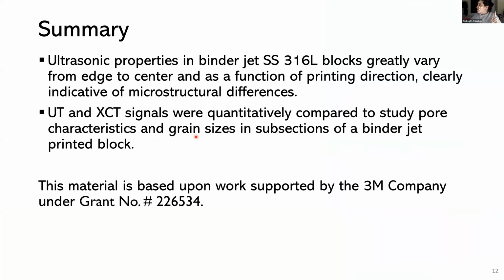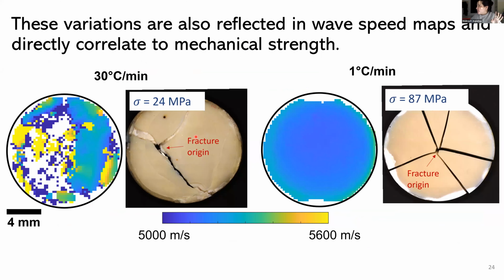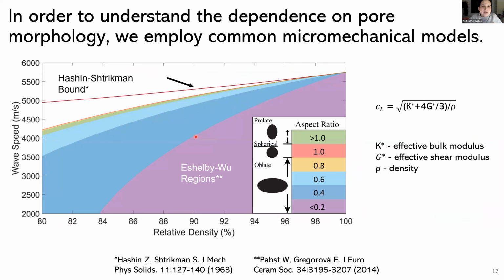Yes. I just stopped sharing, but I'll share again so I can make sure I'm looking at the right thing relative to what you're asking. It was in the cold sintering portion, right? So these maps are actually analytical models. This Eshelby-Wu model at the bottom, that Pabst and Gregorova paper, gives you the effective modulus. You can get the effective bulk modulus and effective shear modulus as a function of that ratio or that shape. Then we evaluate it for the ranges that we know to be relevant for our case, and convert those effective moduli to wave speed using a simple P wave modulus equation.